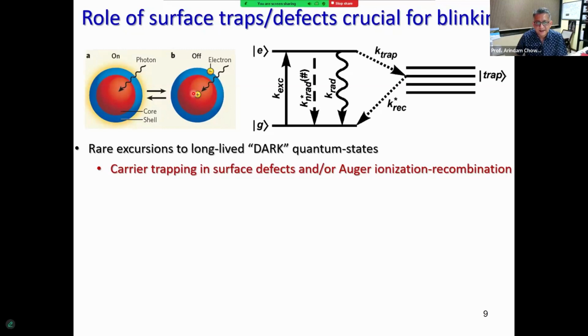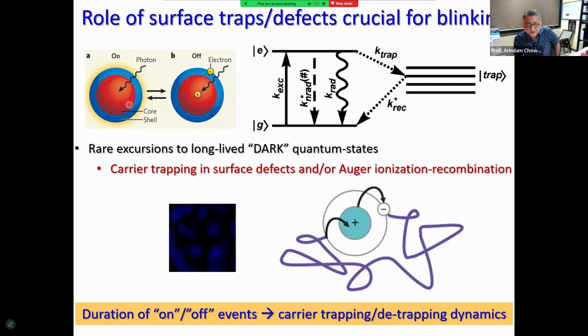But once in a while, a rare event can happen when the electron can get trapped on the surface. And there are many trap states, for instance, near the surface or surface defects. And this electron or the hole can get trapped. And once it gets trapped, then essentially your ground state is depleted. This nanocrystal cannot absorb any further light to generate excitons. And even if they do, they recombine under non-radiative channels. So essentially, once you see the light coming out, that would mean that this process of going up to the excited state and going back to the ground state is going on. And if there's a charge trapping that has happened on the surface, then the light has been turned off, it cannot absorb or emit light, and you have to wait until the electron or the hole comes back and recombines, and you have a neutral species.